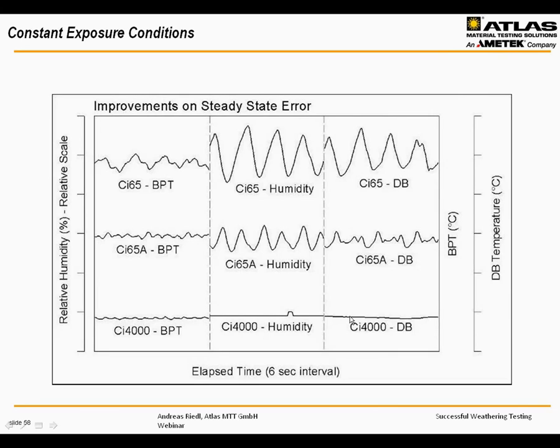And here you see three different generations of Atlas instruments: a CI-65, a CI-65A, and a CI-4000. And you see you may program the same levels, let's say 50% relative humidity, 65 degrees Celsius black panel temperature, and 40 degrees Celsius chamber air temperature.